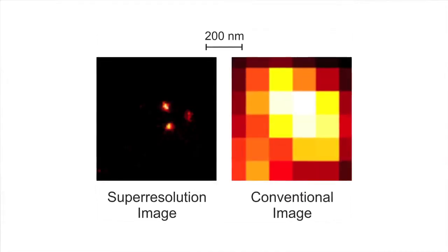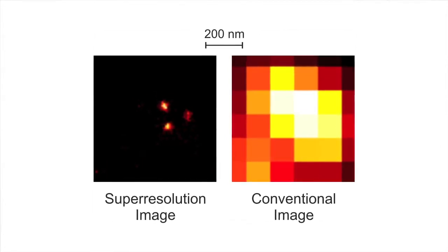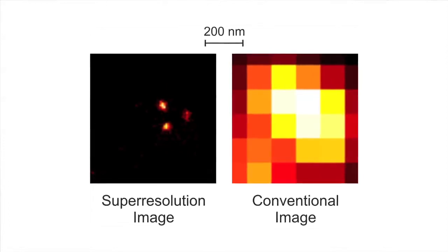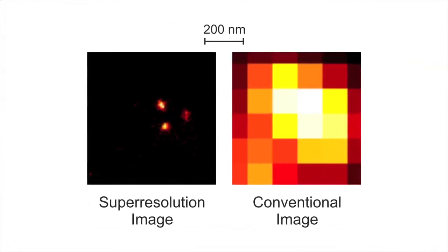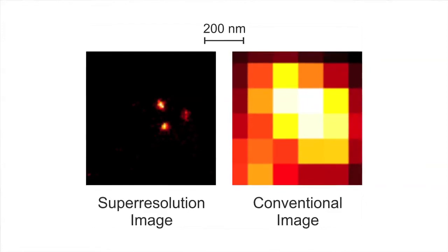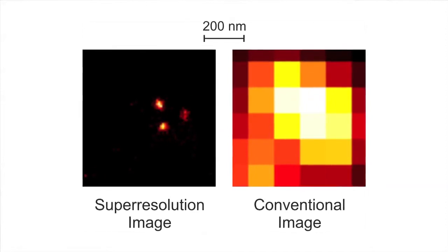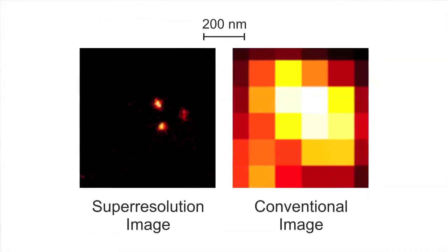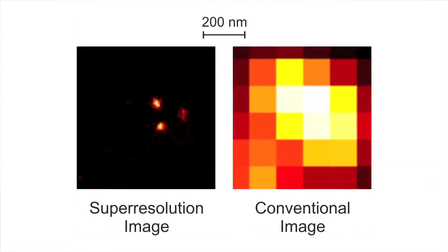For example, we can trap these molecules inside polymer nanoparticles and then deposit the resulting particles on glass. We can image them acquiring in sequence multiple images, and in the resulting reconstructed map it is possible to identify individual particles even when they are separated by distances close to 100 nanometers. In contrast, a conventional diffraction-limited image cannot distinguish individual particles — they appear together as a single fluorescent spot.